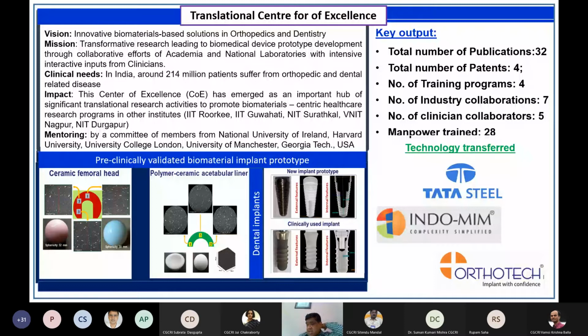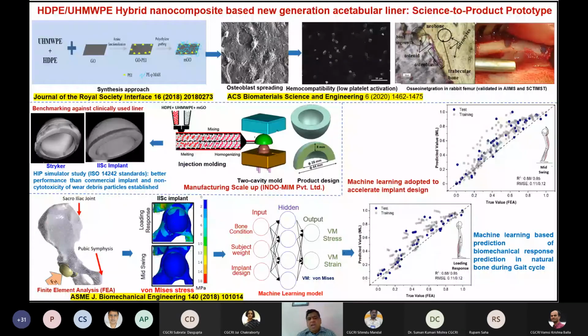So these are some of the statistics in terms of total number of publications and so on, and this technology is being transferred. Just to give you one example of a product which has come out from the center, the HDPE UHMWPE hybrid nanocomposites, where a very small amount of graphene oxide has been added, because we have to be careful in terms of the carbonaceous reinforcement, because it should not cause toxicity to the materials.